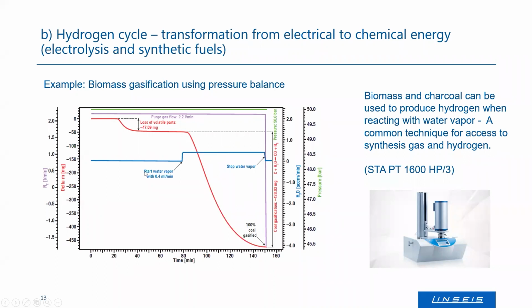If you couple this to a mass spectrometer, you can quantify the amount of gases that come out of your system, and then you can start playing around using catalysts, using pressure steps, using lower or higher amounts of water steam and so on to optimize that process. So this is one of our customer samples, and we have a lot of customers doing this. That's where we are already very much involved in this, more or less hydrogen generation technique.